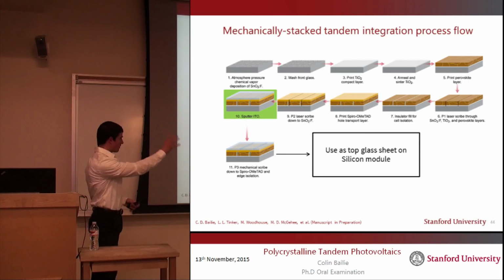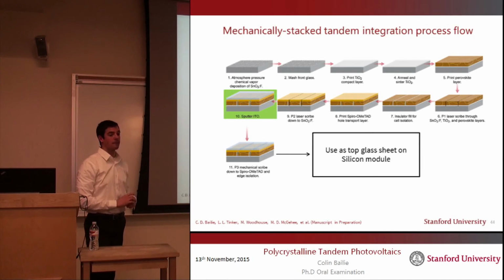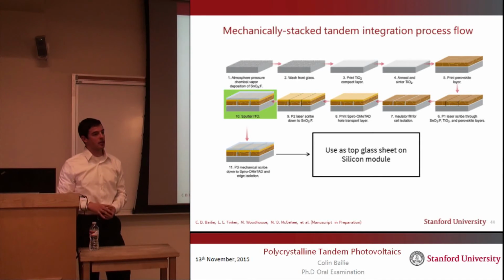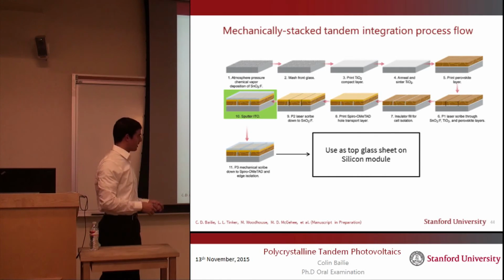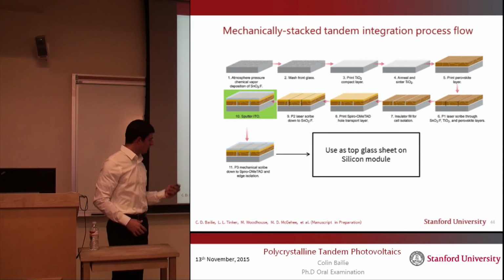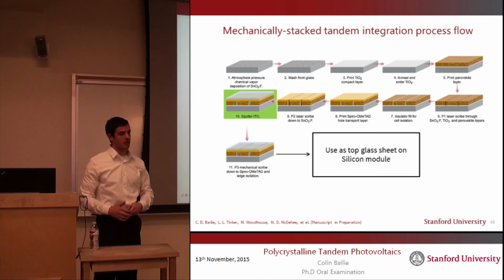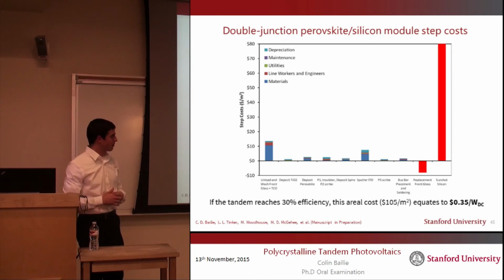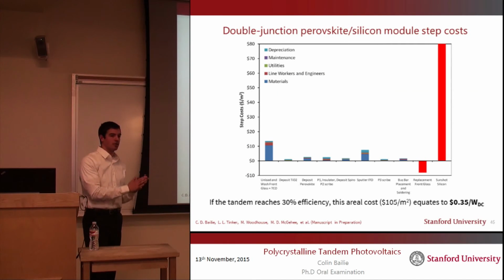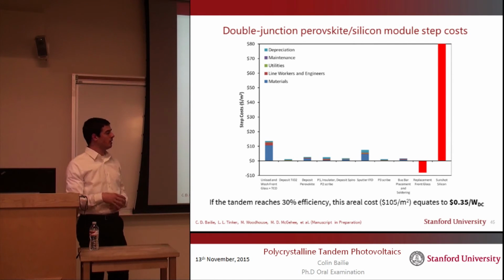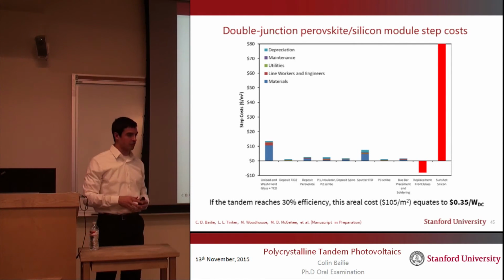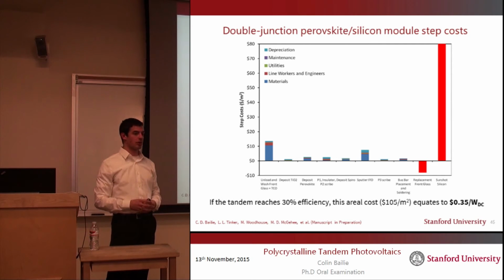And here we're using much the same process flow as before, except that in step 10, instead of depositing a metal, we'll deposit a transparent conductor. And we'll use this as the top glass sheet in a silicon module. And if we assume this silicon module is the DOE SunShot 2020 silicon module, then it'll be about 20% efficient and cost $80 per meter squared.